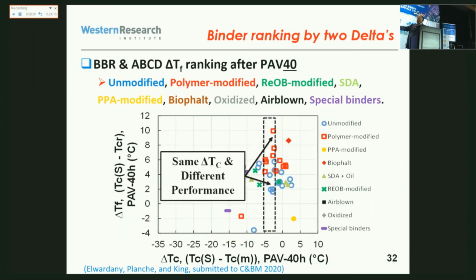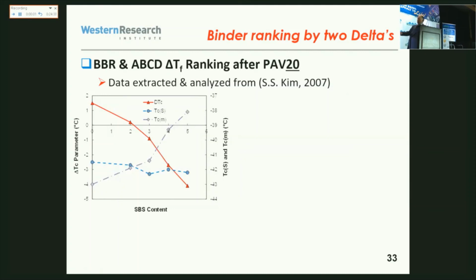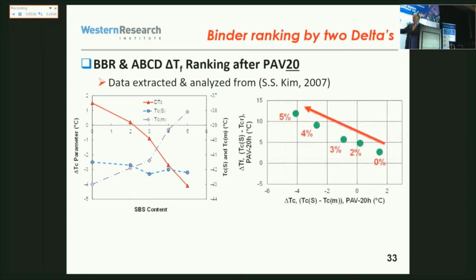Then if we take a given level of delta TC, for example, -5 would be rejected in most states. But if we look at the performance, some of them have very good delta TF, and we have field data showing that, yes, they perform well. So this is giving the credit that we're looking for polymer modified. If we go back to this slide that I already presented, which showed that adding more polymer was bad according to delta TC, well, if we look at delta TF, it goes the other way around. So now, polymer modified are performing well just as they are supposed to do. So this is going in the right direction.